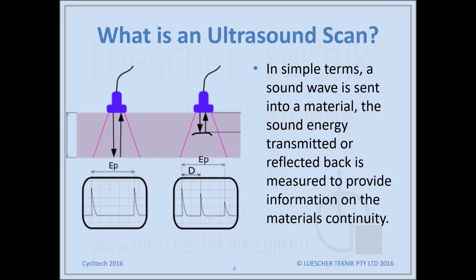So what is an ultrasound scan? Very basically, you send a very high frequency sound wave through the part, and you listen to what is either coming back in this case, or what's transmitted through the part. So if we look at this example, we've got the material, that's the thickness through there, and that's represented by these peaks across there. So that's your front surface, and that's your back surface of the part.